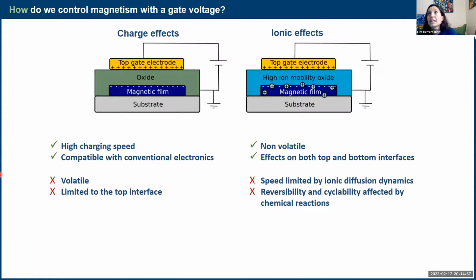And another thing that is still something that the community is working on a lot is the reversibility and the cyclability. Because as we will see later, these ions don't just move around. They strongly interact with the atoms in your magnetic film, for example, inducing oxidation or reduction. And this is something that can affect the reversibility of the effect and also the cyclability. So if you go back and forth 100 times, you might degrade your material at some point. And this is something that the community is working on a lot these days. So I'm going to focus on the ionic effects today. But before I do that, I want to show you a few works that have been done on charge effects for you to get an idea of what can be done there.